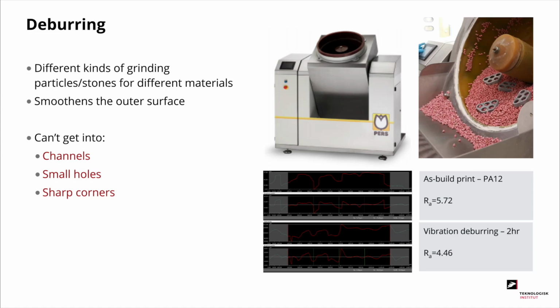If the parts are left in the deburring machine for too long, there's also a tendency for the edges to get rounded off. So if you have some external sharp edges, then they will be rounded off if you keep it in the process for too long. In the graph below, where deburring has been done, we can see how the surface roughness changes the longer we leave the parts in the deburring machine. In this example, we have a raw part, and we have a part that has been deburred for about 2 hours. So it's all about finding the middle ground between obtaining the right surface roughness and not destroying the tolerances that you have on your part.